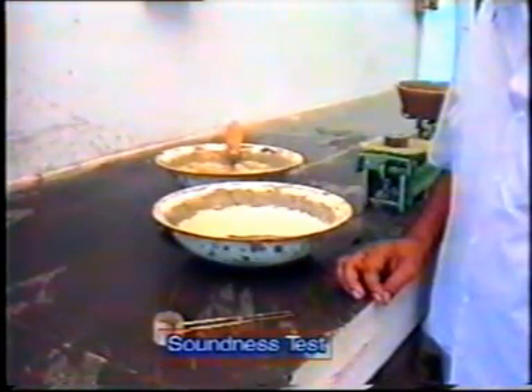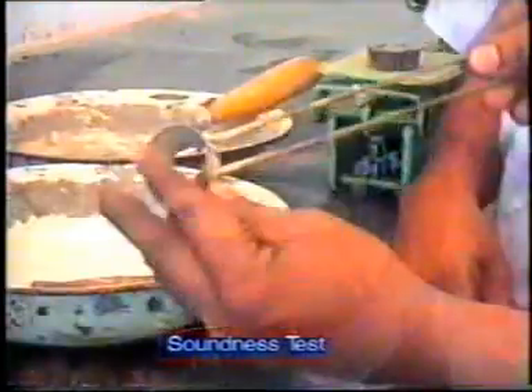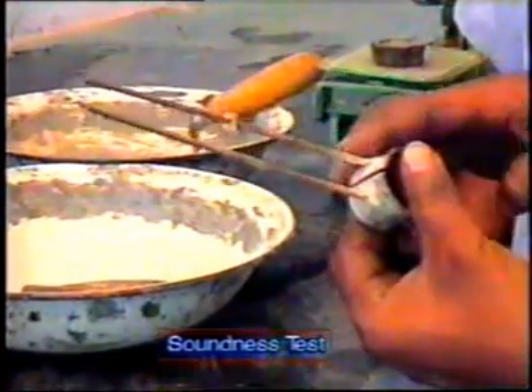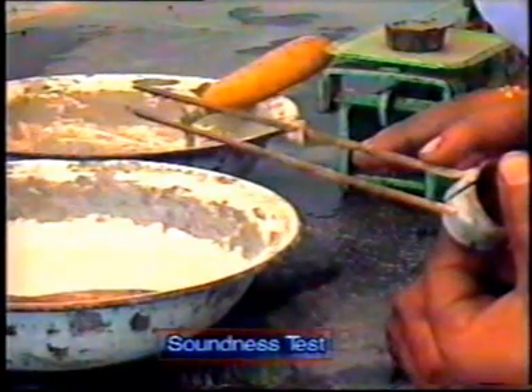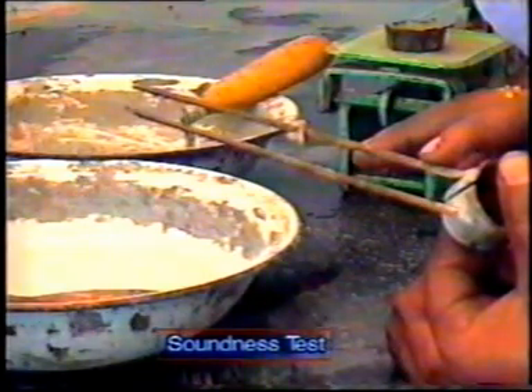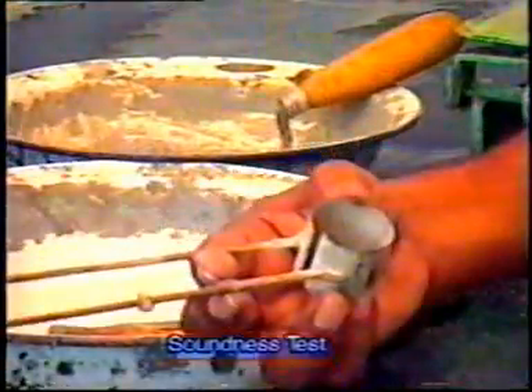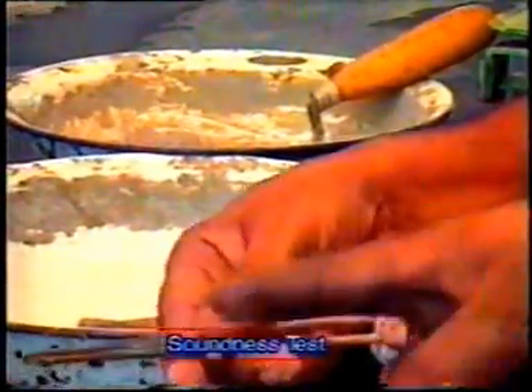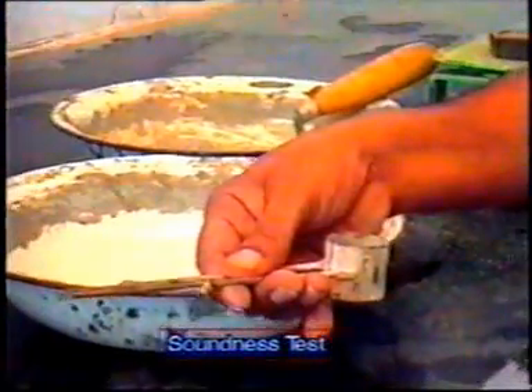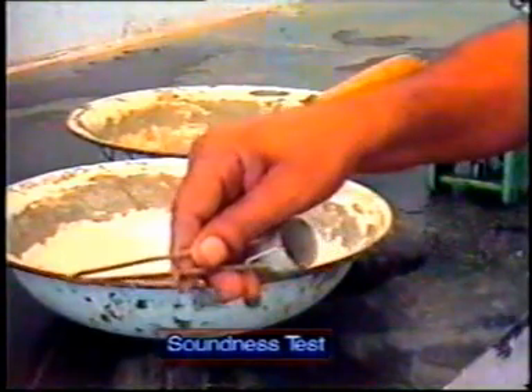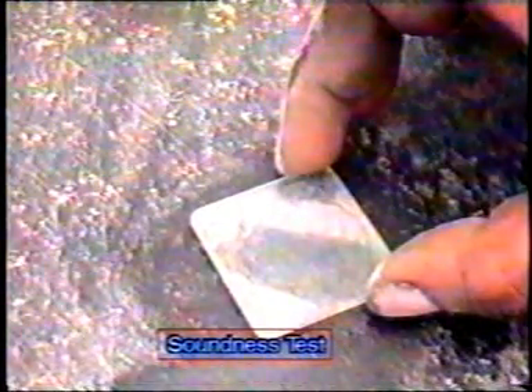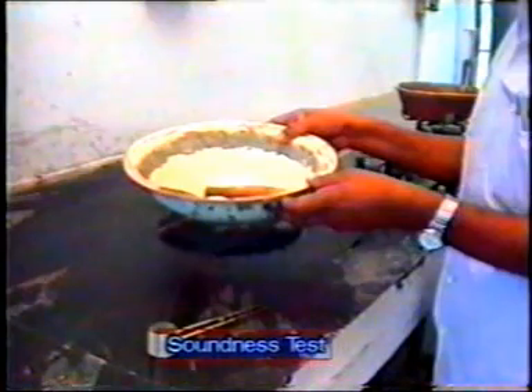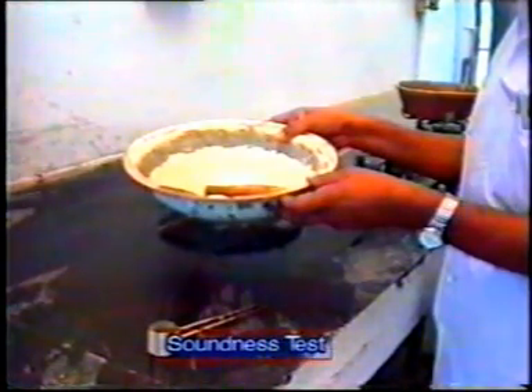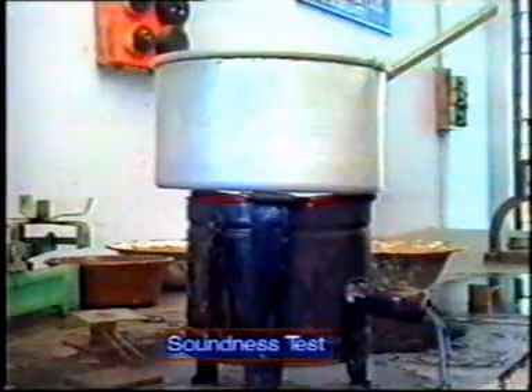This apparatus consists of a small split cylinder of spring brass of 0.5 mm thick, 30 mm internal diameter and 30 mm height. On either side of the split mold, two indicators are attached with pointed ends. Length of these indicators is 165 mm. Non-porous or glass plates to cover the apparatus on top and bottom. Mixing dish, small trowel, stove and dish for heating to boiling temperature.